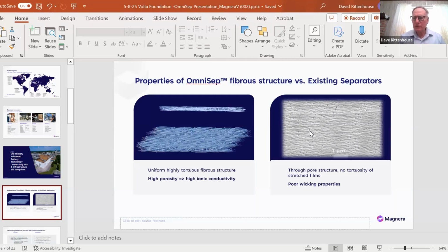And in contrast, this is a stretched film, and it might be of interest to understand this a little bit, to understand the difference. So these things that are running in the cross direction that look like rungs, those are actually crystalline portions of the polypropylene that is used as the base to make stretch film separators, such as the Celgard. And these little teeny tendrils here, it's actually the amorphous part of the polymer. And when those are stretched in this direction, there's a separation, or breakage, between the adjacent crystalline areas, and these little tendrils are what actually form the pores.